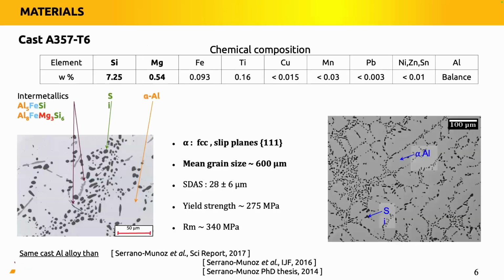The first material is a cast aluminum alloy with silicon and magnesium, which is very well known. This is A357 in the T6 state. This is, I could say, a classic aluminum-silicon-magnesium alloy. This alloy has been produced by the French Research Casting Center in Paris. I emphasize the fact that this is exactly the same alloy produced also in other research projects published by Serrano, Munoz and co-workers approximately 8 years ago. So we were able to take the results of the literature and compare their results on surface cracks with our results on internal cracks.